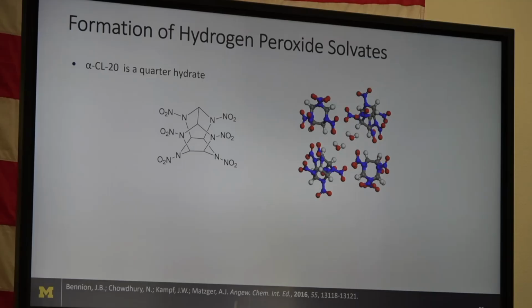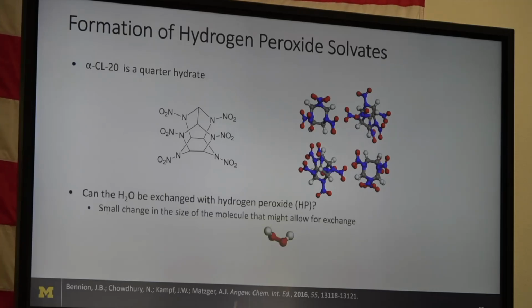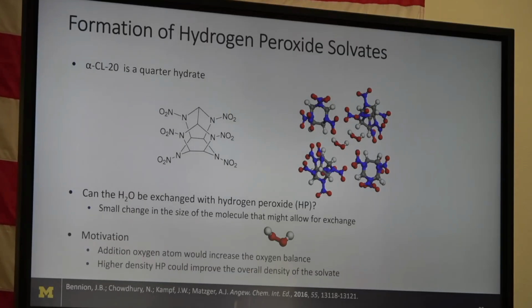But we thought, you know what looks kind of like water? Hydrogen peroxide. Maybe we could get that in there? So that was our thought experiment. And then we were able to actually get some. So first we started making it, and then we found we could actually get 98% hydrogen peroxide. And so this should improve the oxygen balance and certainly should improve the density of the solvate as well.